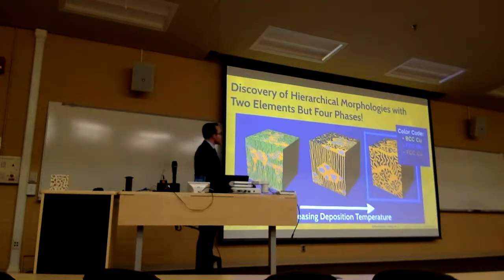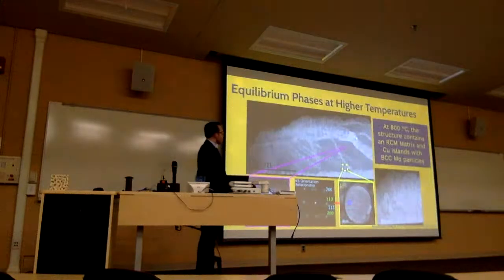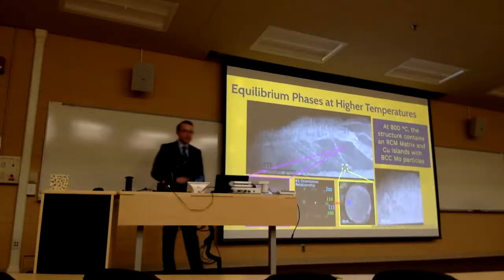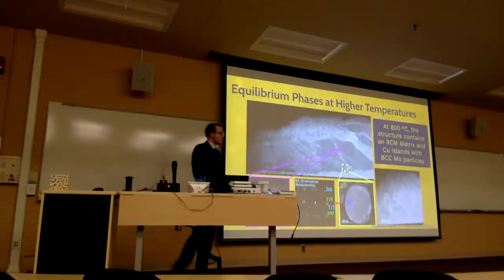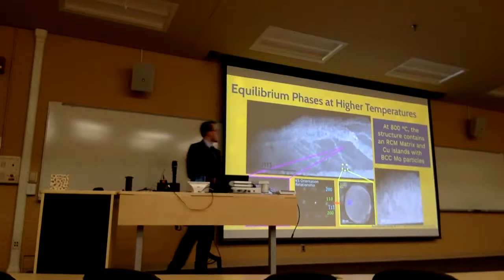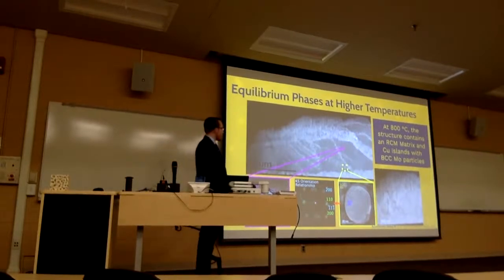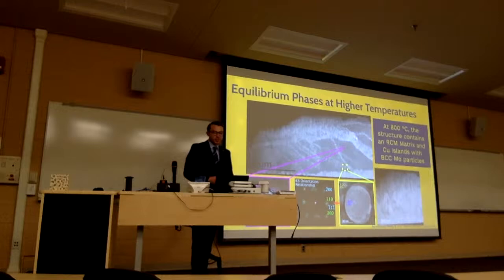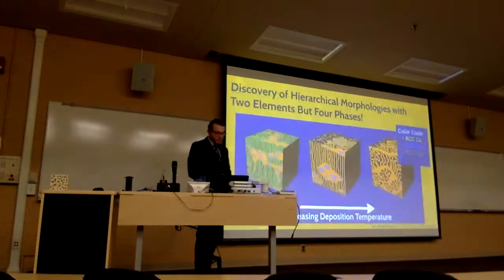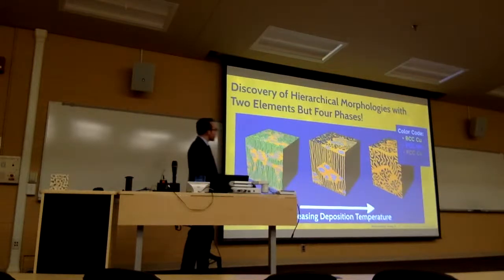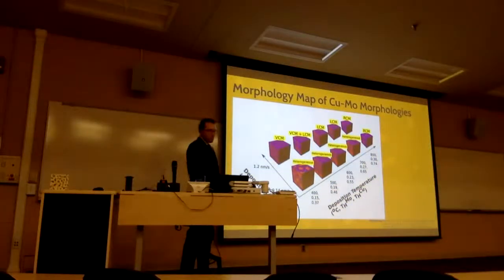At the highest temperature, you can see where this is going. We've coarsened the sample again quite considerably. What we can see is that we've actually designed moly particles inside of those islands that are the equilibrium crystal structure, or body-centered cubic crystal, for the moly particles. And again, the interface with copper is in a Kurdjumov-Sachs orientation relationship. So here's again a summary of those results in schematic form. We apply them to our morphology map that we described before.